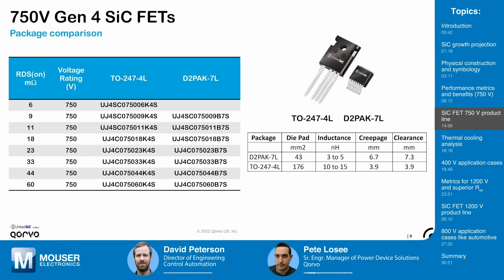In the table on the right, we're basically showing a side-by-side of the parameters you might get from a 247 and a D2PAK 7-lead. Right? And so in the D2PAK 7-lead, you can increase your creepage and clearance distance while reducing your parasitic inductance down to, let's say, 3 to 5 nanohenries versus the more inductive leaded TO-247 through-hole part where you may get 10 to 15 nanohenries of inductance.